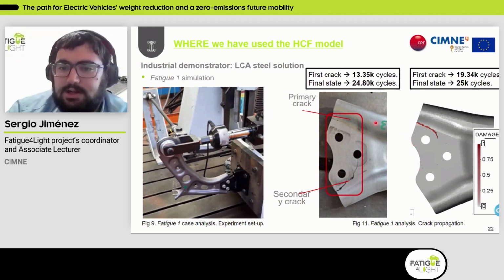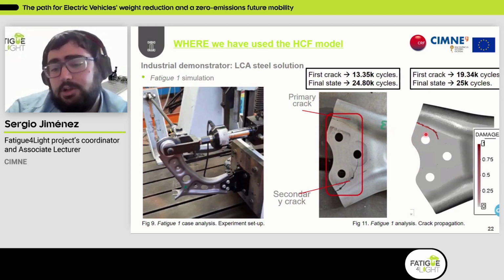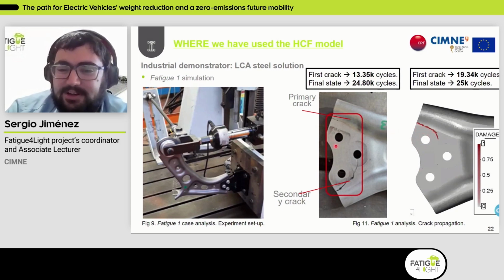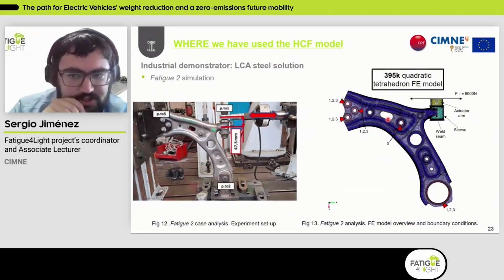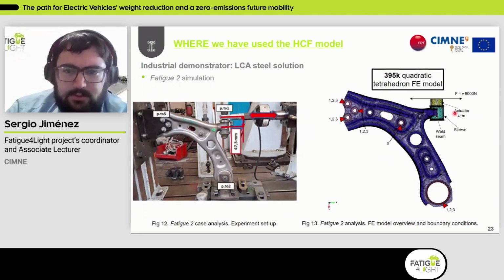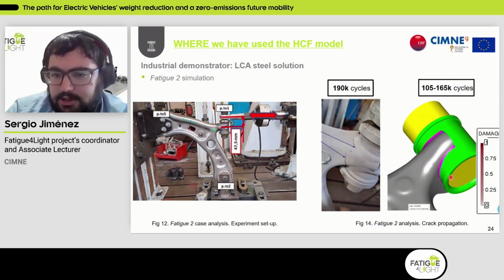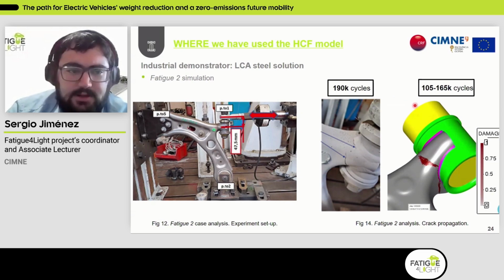And what we obtain is, we capture perfectly the crack pattern obtained experimentally, identifying this first crack and then the secondary crack exactly in the same manner in our model, and also in terms of number of cycles. So this was pretty good, but we also performed another simulation for another case study for this steel lower control arm, where now the force is being applied into this element here that is being welded to the rest of the lower control arm. And this is the type of result that we are obtaining from the simulation, again, capturing the type of crack patterns observed experimentally, and also with a good agreement in terms of number of cycles.